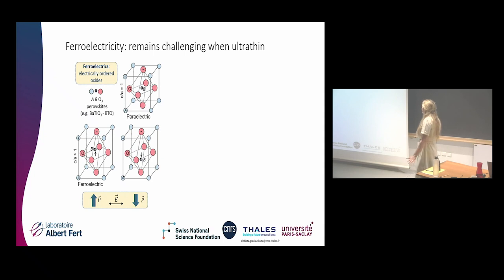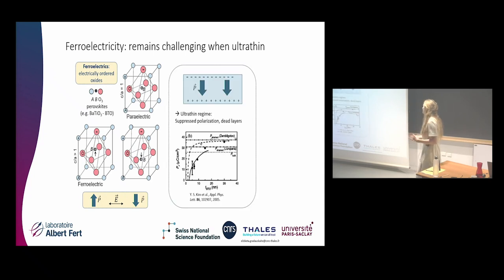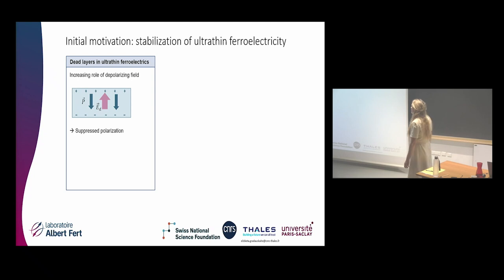Unfortunately, there are still a few challenges remaining that prevent the integration of such ferroelectrics into devices. What is very annoying in the ultra-thin regime, when we grow our films very thin, which ideally we want for devices, is that the polarization goes down. Already in BTO, around 20 nanometers, you see that the polarization is going down. That's because there are bound charges at surfaces that will never be fully screened, even with metallic buffers, because of the screening length. We end up with this depolarizing field fighting the polarization and minimizing it. In extreme cases, when we go below 2 nanometers, 4 unit cells usually in typical ferroelectrics, we lose the polarization completely. That's what we call the critical thickness for polarization.